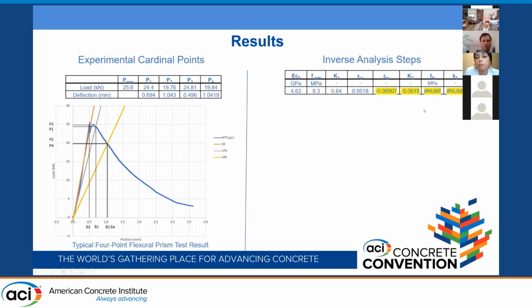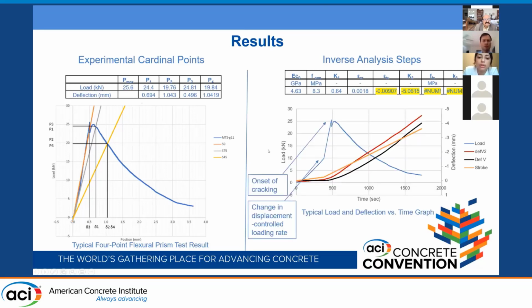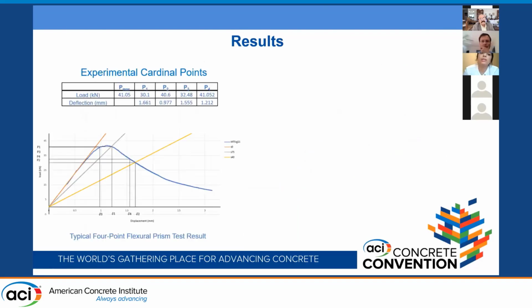This is especially true for the ultimate portion. In this graph, you can see a load and deflection curve versus the time, and you can see here the onset of the change in the loading rate and the onset of the cracking. That was the first sample.